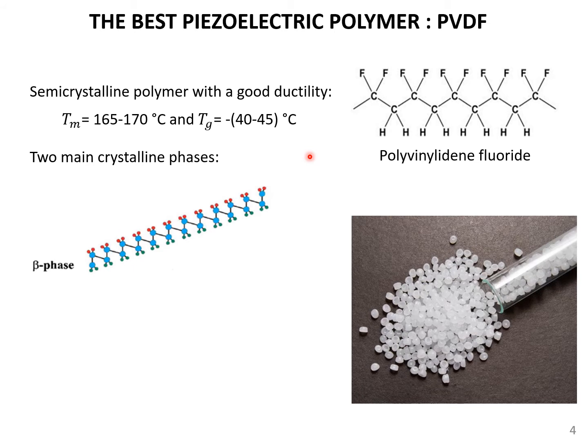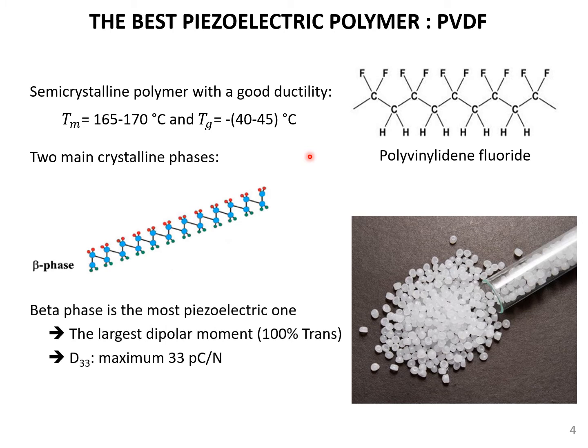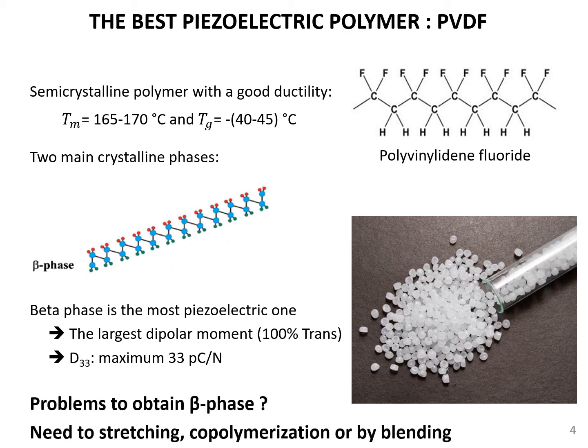To get the best piezoelectric properties, you need to reach the beta phase. This is the beta phase where you can identify all the fluorine in the same direction, giving the largest dipole moment and giving a value close to 30 picocoulombs per Newton.